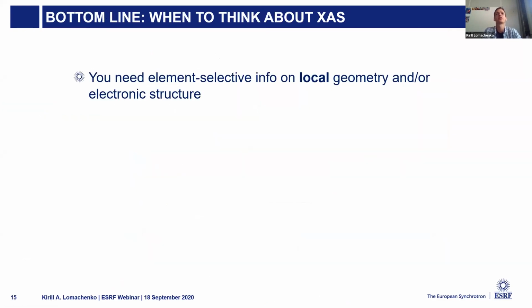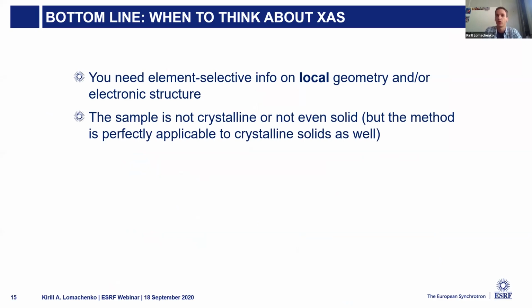So the bottom line: when should you think about XAS? Basically, to cut it short, when other methods that may provide the necessary results under certain conditions do not work. For example, when you need element-selective information on local geometry or electronic structure of particular species, you don't want to use methods that rely very much on long range order, because you want information on local geometry. So when your sample is not crystalline, or may even not be a solid - it can be liquid or some amorphous sample - X-ray diffraction, for example, will not be as precise as for perfect single crystals.